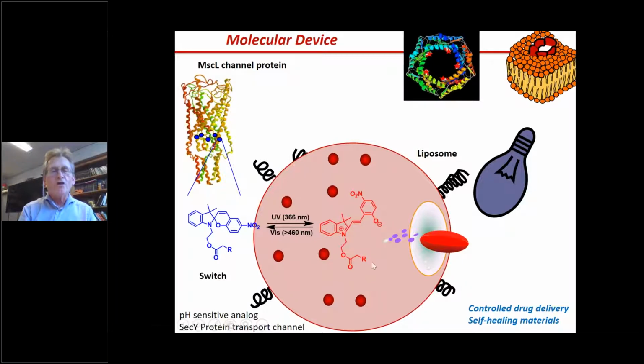maybe. And that works beautifully, because what we did is we could incorporate it in a giant vesicle, like an artificial cell. We could load it up. We can then irradiate, and the pore opens, and we can close and open the pore on demand. So we can now control, using this system, flow through a nanopore on demand with an external light signal. So this is really how we engineer, starting with parts from Mother Nature, the protein channel, re-engineer it to build in artificial switches. And we use that, for instance, for controlled drug delivery.